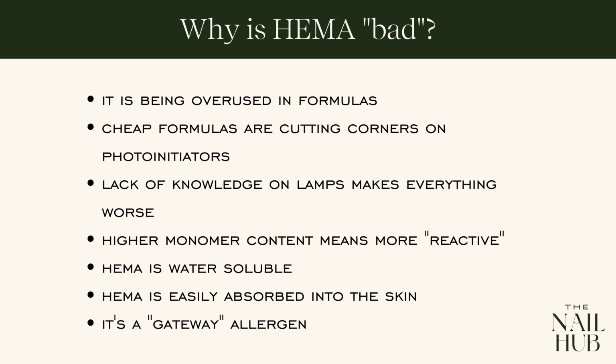HEMA is water soluble, so these monomers are actually able to leach out when we wash our hands. They also leach out when we go to file them or soak them off with acetone. And as we do this repeated process of removing and reapplying our gel, and also wearing our gels for 2, 3, 4, 5, 6 weeks, every time we go to shower, bathe, or wash our hands, some of that undercured monomer can leach out of the quote unquote cured product. It can get onto our skin and our body absorbs it.